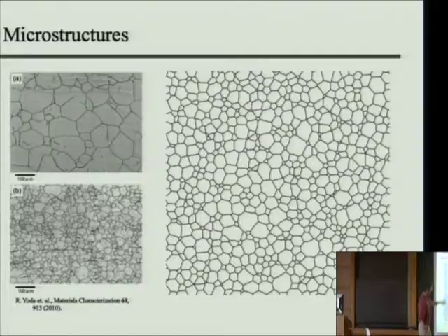And so you could go from this to this in the time you could sit at the laboratory bench and wait for that to happen. If it was steel, depending on the alloy, you would probably have to be at 600 degrees Celsius or so. That's what the word anneal means? Yeah, anneal just means to raise it to some elevated temperature and allow it to stay there. I've heard it used all the time. Yeah, there's actually a great deal of science involved in it.